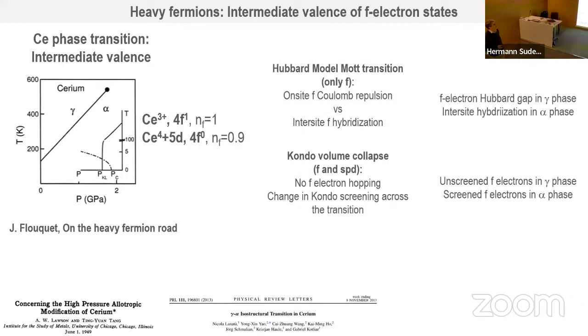So usually when you start speaking about f electron states, it is nice to start with this system here. Cerium is actually a unique material, as far as I know, it is completely unique. You know that we have the phase diagram of water, and you know that we have a critical point. We have a point above in pressure and temperature where we can make no difference between the liquid and the gas. And there is no critical point in a solid, that's what we tell students, because usually when you have a transition in a solid, you have a structural phase transition, and therefore you can always differentiate and you have no such situation.